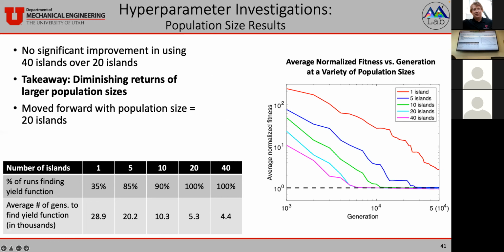Population size, what I'm showing here, we do expect larger populations to perform better. You have more equations, more diversity, but we do see diminishing returns, which is an important takeaway for using GPSR in practice. You don't want to be using up all your computational resources in practice. So we see that 20 islands, once you get to a normalized fitness of 1, where the yield function is at, it pretty much meets up with the 40 islands curve. And so for these reasons, we moved forward with a population size of 20 islands.